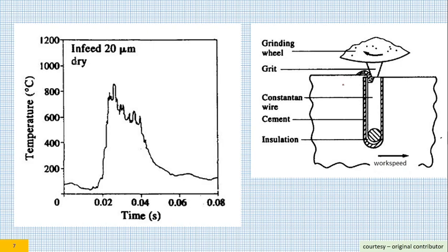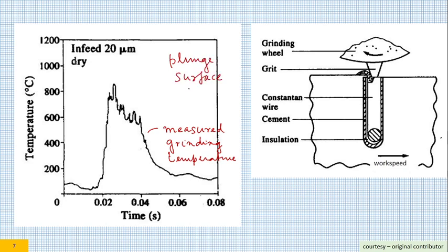Now let us look at the measured temperature. So this is the actual measured grinding temperature in plunge surface grinding. This was at an in feed. At that time, the down feed used was 20 micron, and the environment was dry.